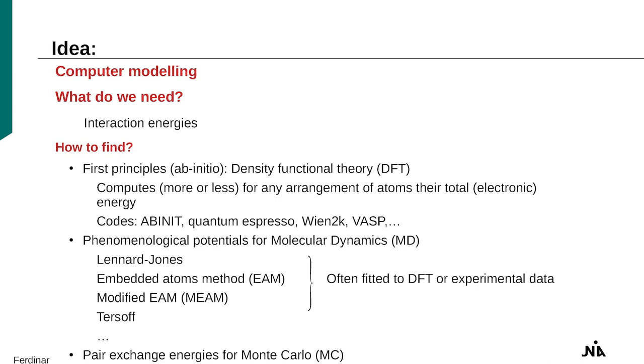Here shows this Lennard-Jones potential, which has this shape as I already showed, and it has just two parameters, A and B. So it's a power 12 and a power minus 6 function of the distance between the atoms here. This power 12 has no real justification. It was just chosen because it's so simple to work with. It reflects this steep increase here. The power minus 6 is the attractive part here. That's why it has a minus sign here. This parameter A describes the depth of the potential, and the parameter B the spatial scaling here.